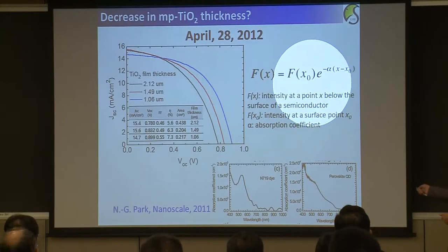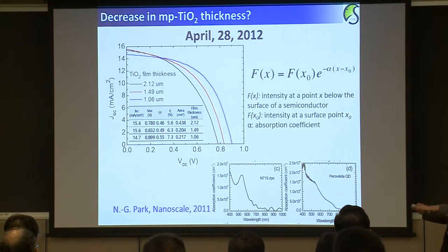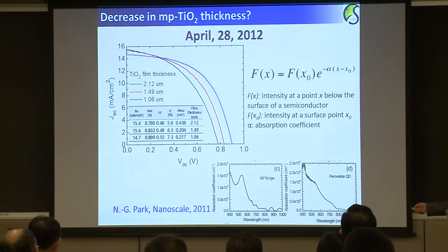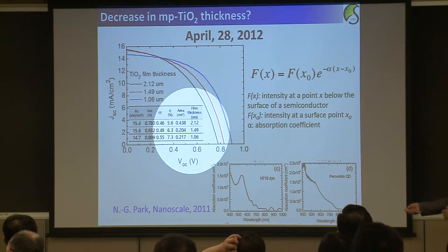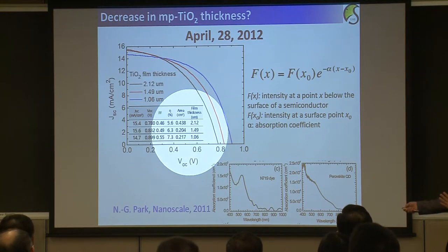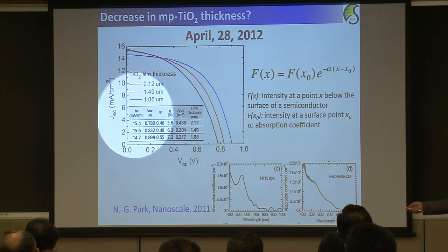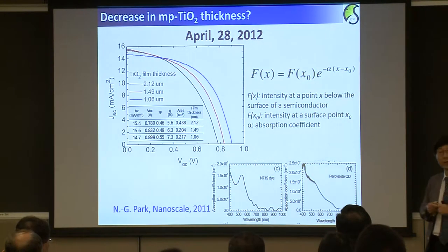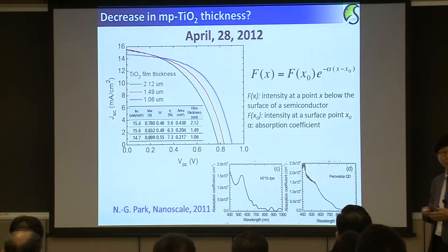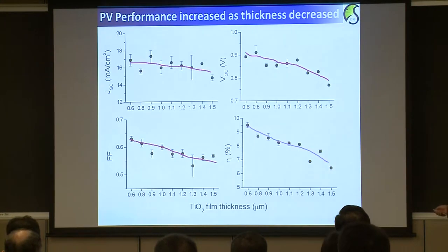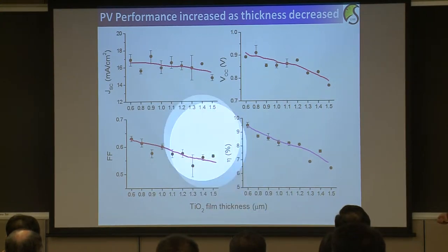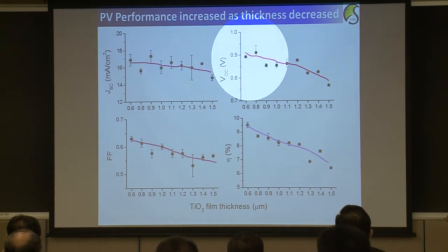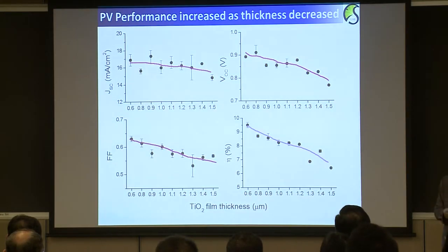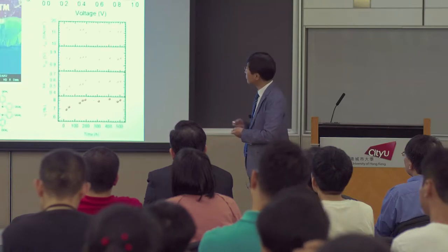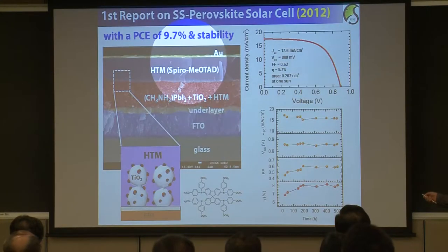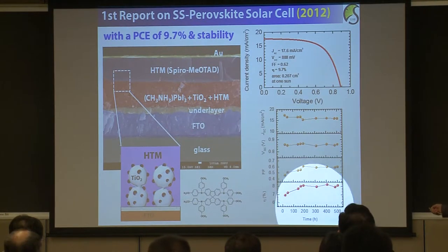So based upon this inverse proportional relationship between the absorption coefficient and film thickness, instead of increasing the film thickness, she wanted to decrease the film thickness from 2 micrometer to 1 micrometer. And then she found a slight increase of the efficiency from 5.6% to 7.3%, because of the increased open circuit voltage and fill factor without sacrificing the photocurrent density. So her expectation was right. And then she further decreased it to 0.6 micrometer. Without losing photocurrent density, because of the increased open circuit voltage and fill factor, she could get about 10% efficiency. And eventually 9.7% efficiency with 500 hour long-term stability without encapsulation.